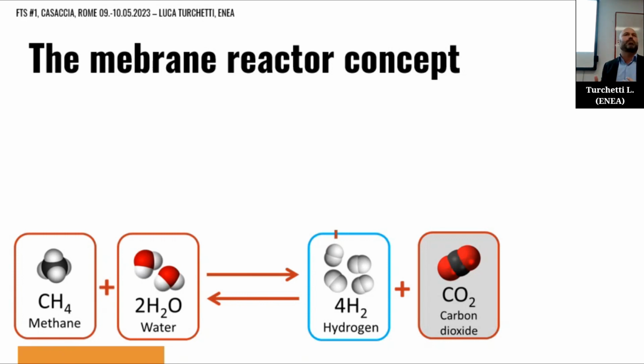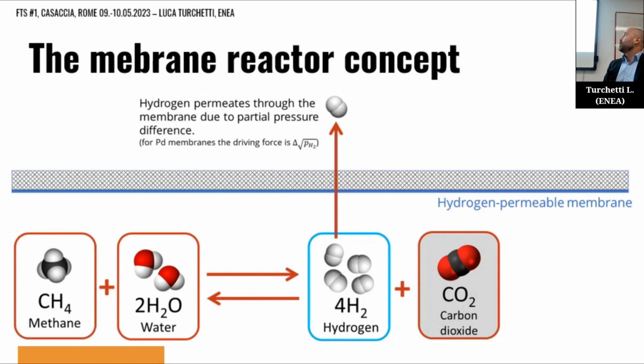At low temperature, this conversion is very low, 10, 20, 30% at maximum in the best feed conditions, while for this process to be industrially applicable, you want to go to higher conversion. So how do you manage that? You introduce in the reactor a hydrogen-permeable membrane that allows the passage only of hydrogen, and you remove hydrogen from the reaction space. This will push the forward reaction and allow you to achieve higher conversion.